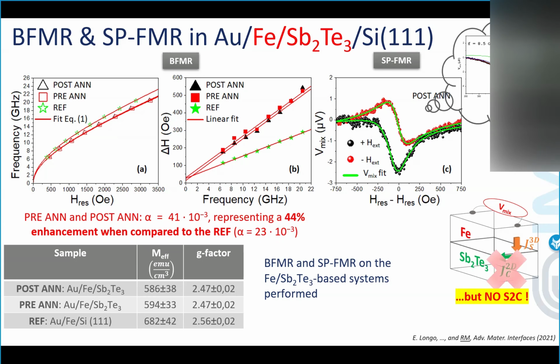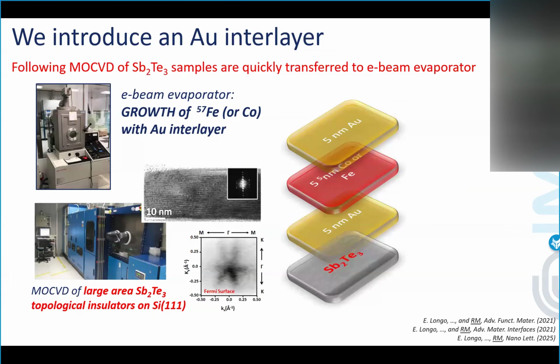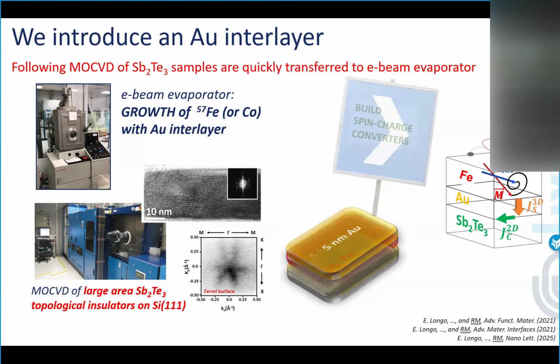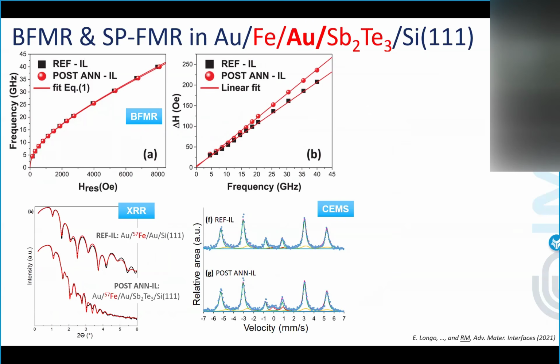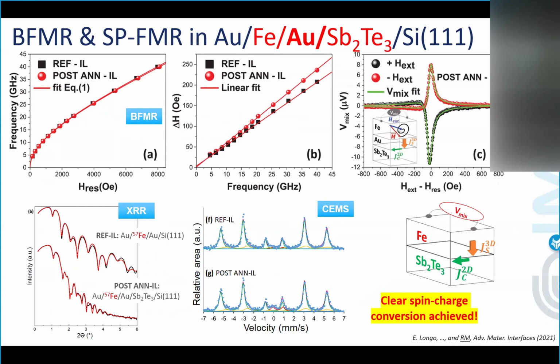So the idea was to protect somehow from the magnetic perturbation of the iron the topological surface states of our material, and we have done this by changing a bit the strategy and introducing a gold interlayer between iron and the topological insulator, and go again to our spin charge conversion. And of course, we checked by conversion electron Mössbauer spectroscopy both samples, the reference and the one with the topological insulator. We see mostly pure alpha iron, and in this case, we have been successfully looking and measuring a very clear spin charge conversion. So this is an example of how Mössbauer spectroscopy, in this case conversion electron Mössbauer spectroscopy, can be really helpful in understanding some peculiar, interface-based properties in very new and interesting materials such as topological insulators.